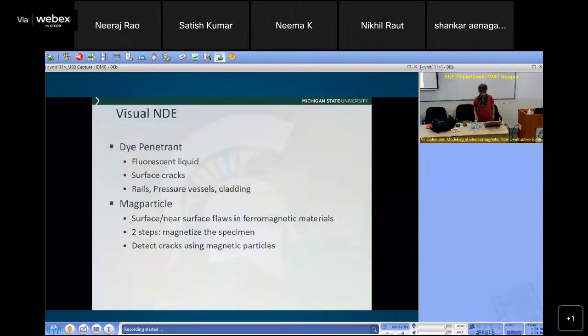So then you magnetize the rails. Then there's a little local field near the cracks. And when you again pour these liquids with the ferromagnetic material, those particles get attracted by the magnetic field and stick to the crack. And then once again, you use some kind of ultraviolet light and pick up those magnetic particles. So these are pretty primitive. Things have gone a long way. If you have to go through 100 miles of rails and do this locally, it's going to take you a couple of years to inspect. So that's not what you want to do.